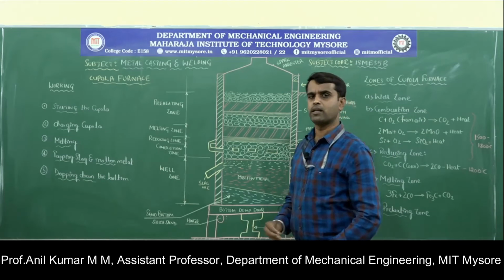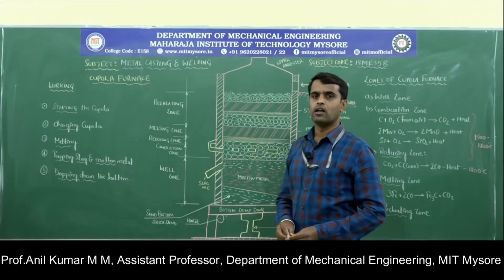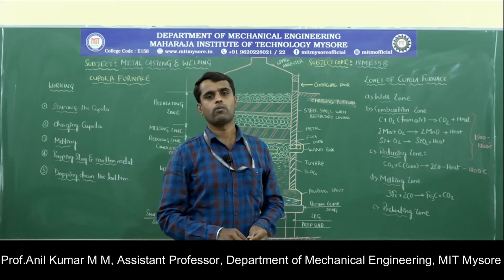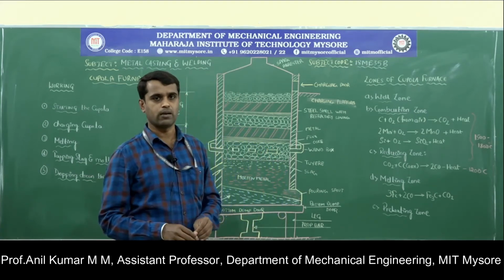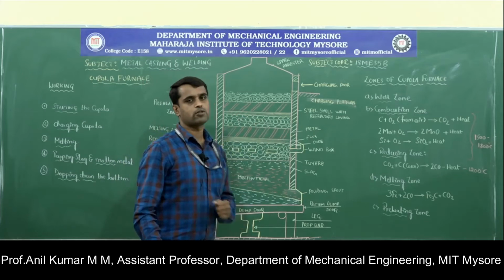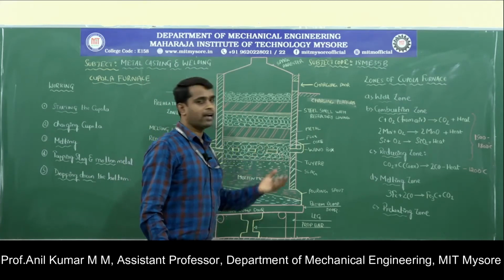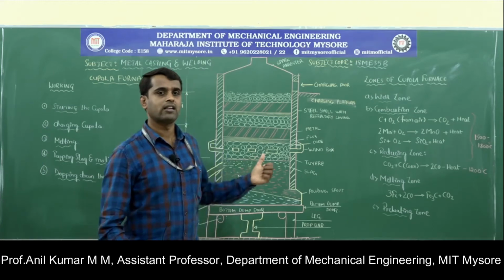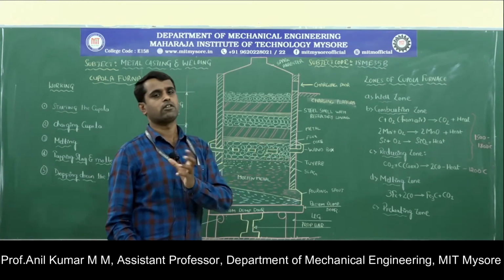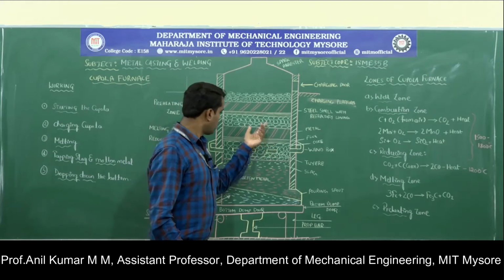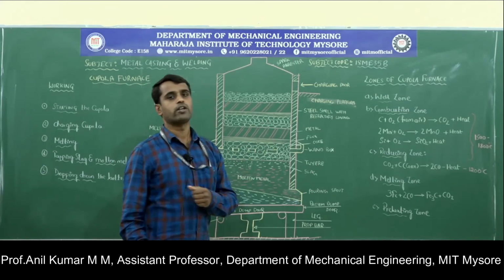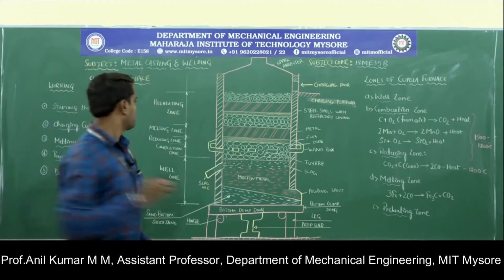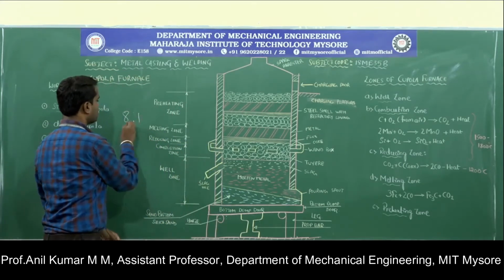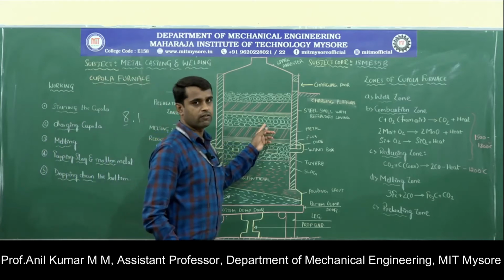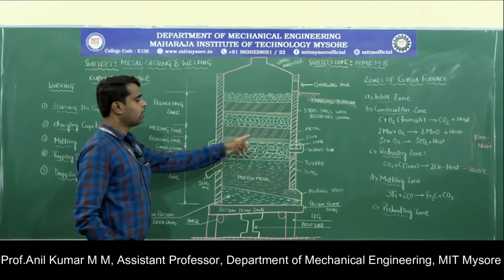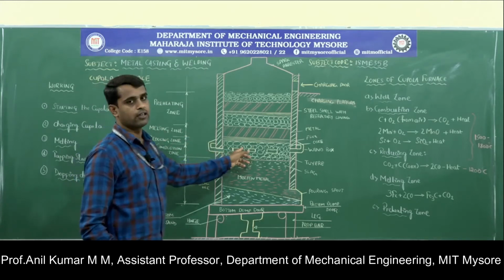The commonly used flux material in the cupola furnace is limestone. Other than that, sodium carbonate and calcium carbide are also used as flux materials, but in the cupola furnace limestone will be added. The weight of the flux added into the furnace is 20% of the weight of the coke, and the commonly used iron to coke ratio is 8:1. To melt 8 parts of the metal, 1 part of the coke will be added inside the furnace.